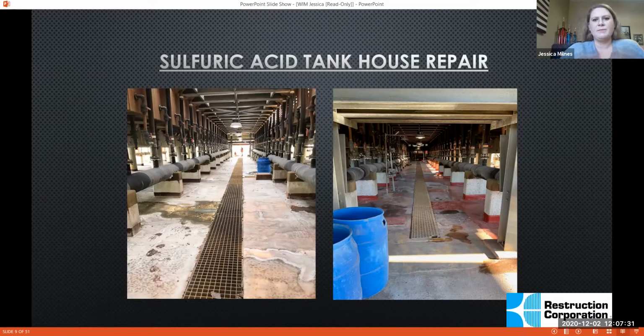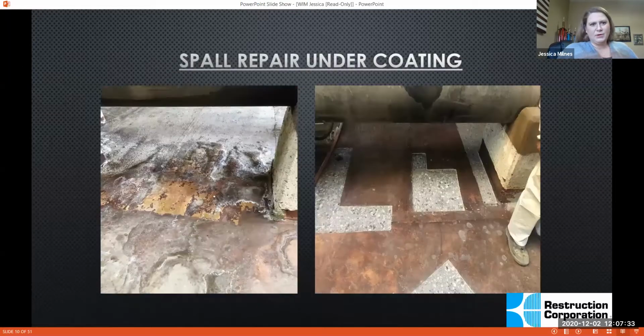So these are some before and afters of our repair. What you can see here is that when this acid gets on the coating and there is any kind of failure in the coating, it gets underneath it and causes this bubbling. So what's actually happening is the coating itself is coming apart from the concrete, but the concrete is also disintegrating. So it is falling apart.